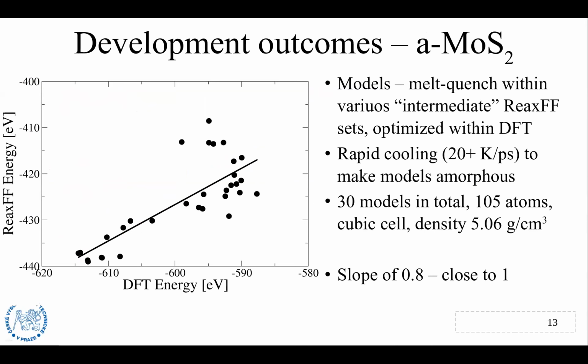I also did some more weird tests. I mean, energies of amorphous molybdenum disulfide models were generated via melt quench within ReaxFF and then optimized with DFT. So I can get energy in DFT, I can get energy in ReaxFF. I plot them versus one another. I get a slope that is not exactly one, but is close enough to one.